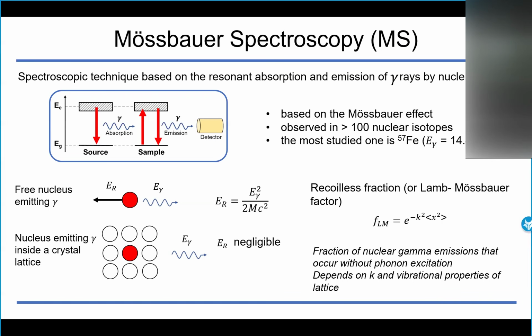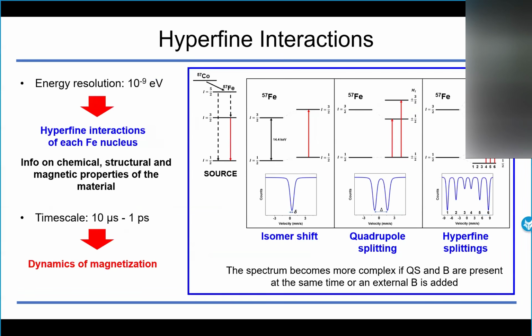To have the Mössbauer effect, we need the process to be recoilless, so the nucleus must emit this gamma ray without recoil. The probability for Mössbauer effect is the so-called recoilless fraction, or Lamb-Mössbauer factor, which depends on the wave vector of the gamma ray and on the vibrational properties of the lattice. So, Mössbauer spectroscopy is a very sensitive technique with an energy resolution down to 10 to minus 9 electron volt that allows to study the hyperfine interaction of each iron nucleus in the sample. So, from the isomer shift, the quadrupole splitting, and the hyperfine magnetic splittings, we gain information about the chemical, the structural, and the magnetic properties of the material that we are studying.